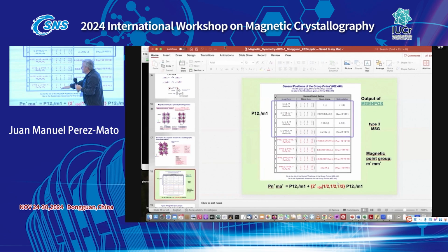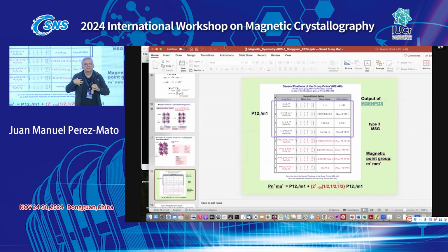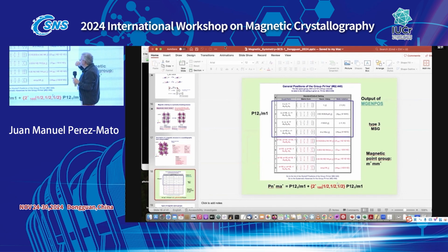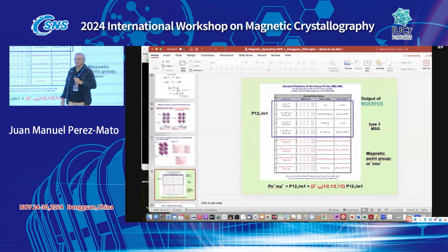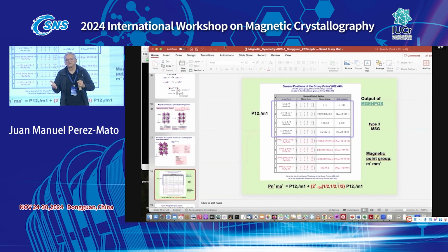And all these red operations here, if you multiply one operation which is red by one which is red, that means that the red is only used in our server. You will not see it in general. It means only that it is time reversal. It is included in the symbol just by the -1 that you have there. So if you take and multiply two operations which have time reversal, the result is what? An operation with time reversal or without time reversal?